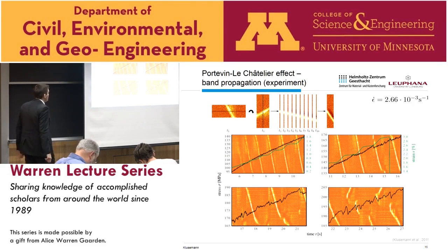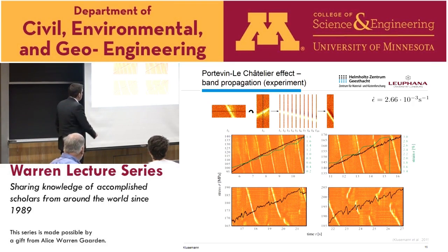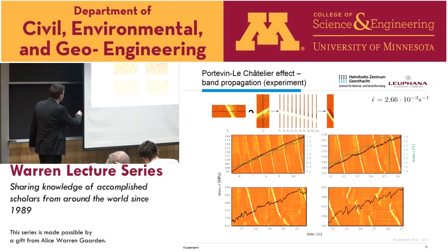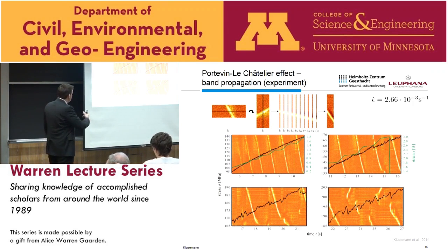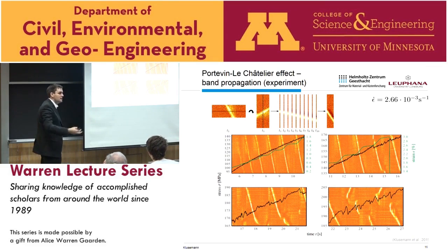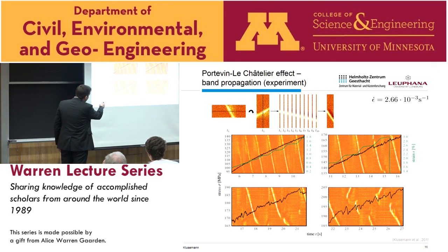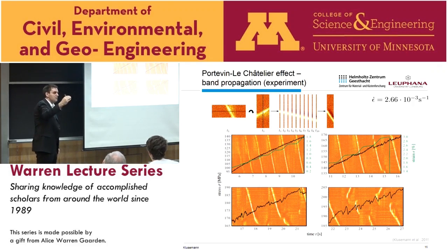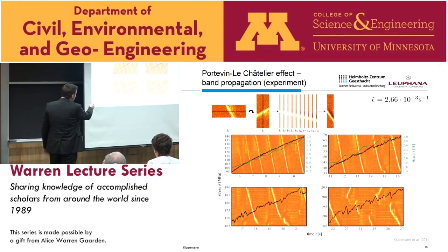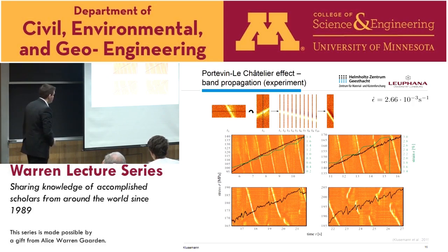Okay, second, we investigated the band propagation behavior. Here the experiment is shown first. In the background you always see the images of the PLC band. They always take one slice out of each time step, and by this we could see a very nice, continuously propagating PLC band in the experiment, which is also nicely reflected in the green line, which represents the strain level. We have this very classical step-stair structure. Every step is correlated to one PLC band.